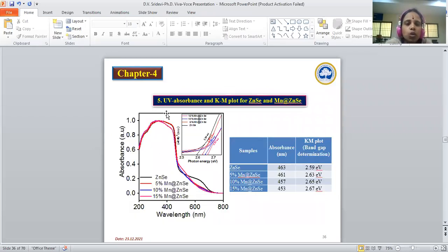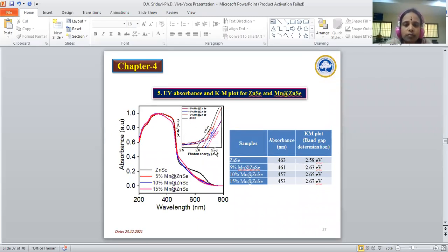This slide shows the UV absorbance and KM plot for zinc selenide and manganese doped zinc selenide nanoparticles. Here the absorbance decreases by doping manganese ion into the zinc selenide nanoparticles, which is responsible for the redshift. And also the band gap value was found to be 2.59 electron volt for zinc selenide, and a small increase in band gap values is found from 2.63 electron volt to 2.67 electron volt when the manganese ion is incorporated into the zinc selenide nanoparticles, which is shown in the inset figure of the absorbance spectra.